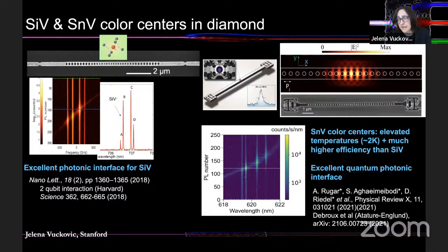They have a transition at 619 nanometers, at somewhat shorter wavelength than silicon vacancy. But also they're inversion symmetric and to first order immune to electric field, which means that they're more stable to DC electric fields. And what is also important is that as a result of a larger ground state splitting, they can operate at somewhat higher temperatures than silicon vacancies. So you can actually obtain the same experiments and achieve the same results as silicon vacancies, but maybe at a few Kelvin temperature as opposed to millikelvin temperature, which is still required for silicon vacancies because of the very small ground state splitting.